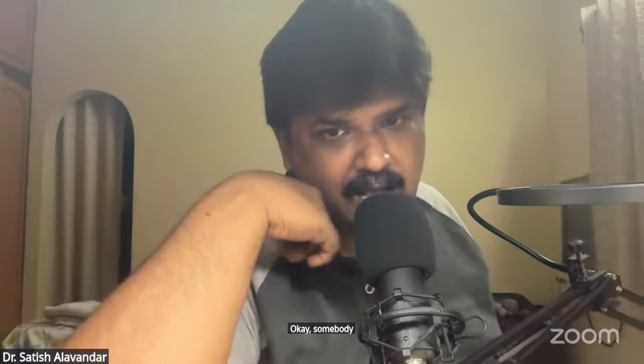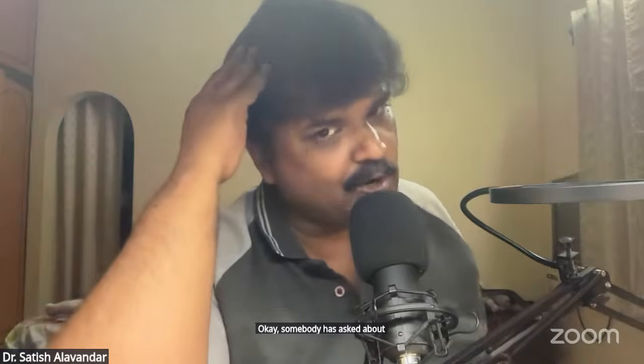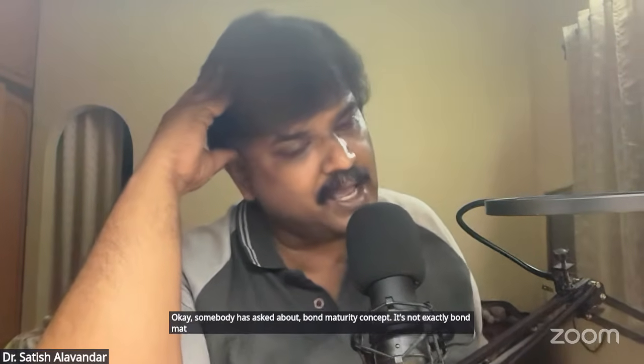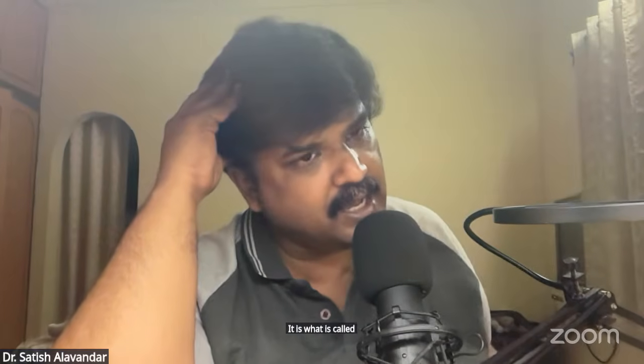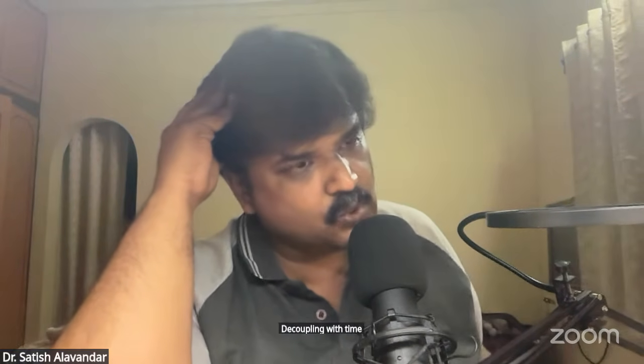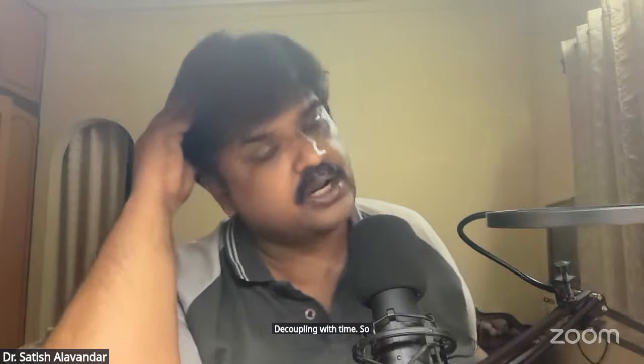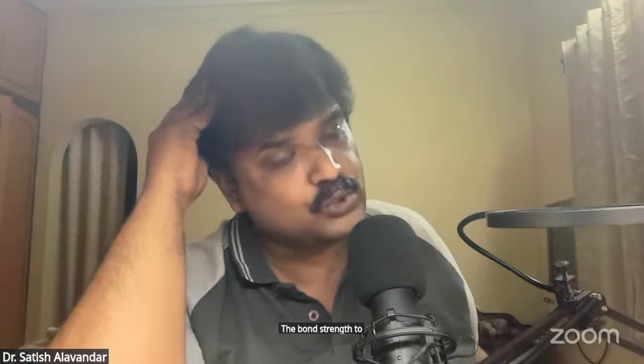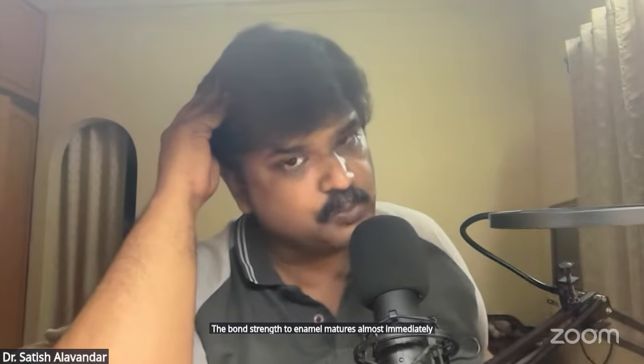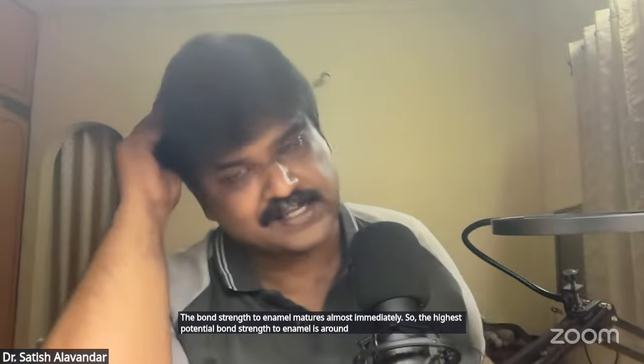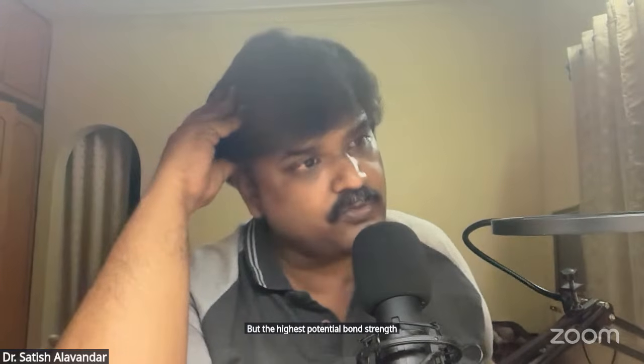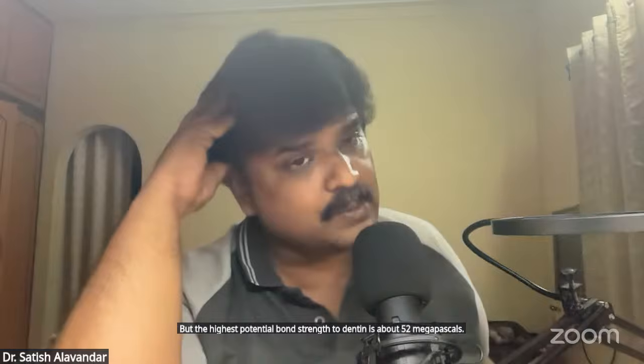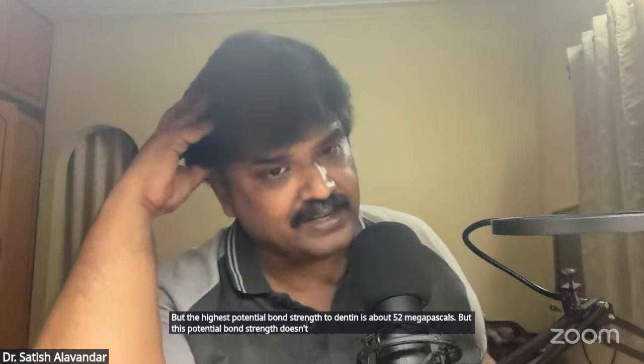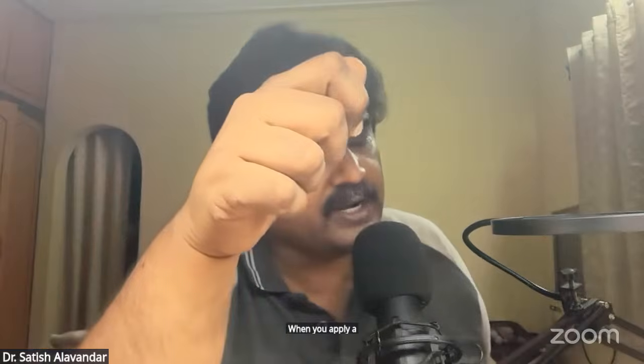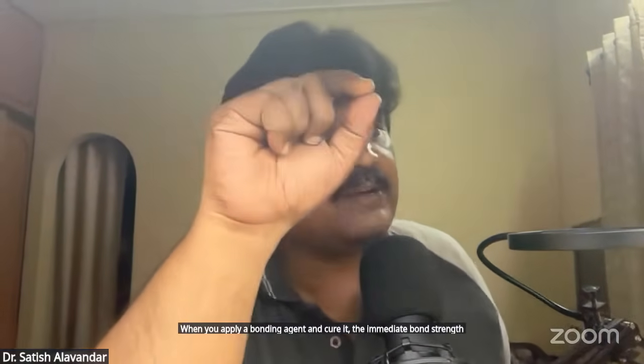Okay, somebody has asked about the bond maturity concept. It's not exactly bond maturity concept. It is what is called decoupling with time. As per literature, the bond strength to enamel matures almost immediately. The highest potential bond strength to enamel is around 35 megapascals, but to dentin it is about 52 megapascals. But this potential bond strength doesn't develop immediately. When you apply a bonding agent and cure it, the immediate bond strength to dentin is only 15 megapascals.